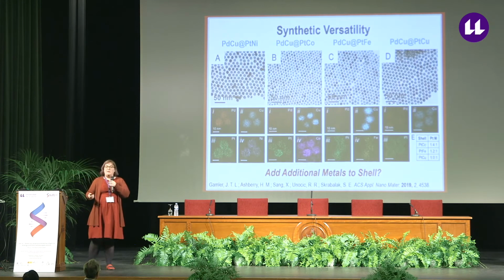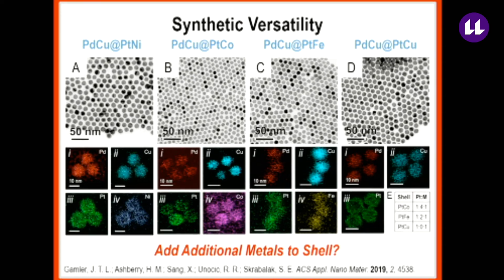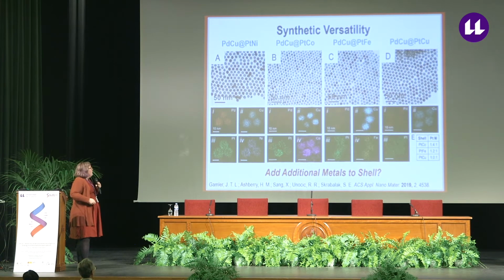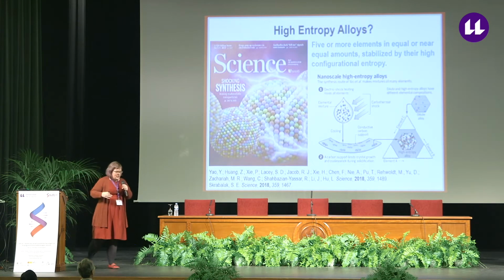And it's relatively versatile in terms of what type of compositions we can access. So in addition to a platinum copper shell, we could achieve platinum iron, platinum cobalt, platinum nickel. If you're familiar with catalysis, these are all the metals and alloys that people are interested in for the oxygen reduction reaction. And we've studied these nanocrystals for the oxygen reduction reaction. They perform a bit better than platinum, but their standout feature is high durability imparted by the intermetallic core to the shell. But in the few minutes that remain, I want to talk about